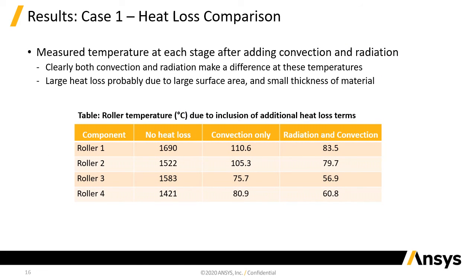So if we have a look at this table of temperatures, we'll see why the different types of heat loss are important. If we look here in the first column, we see that if we just look at the heating due to the eddy currents, we end up with very large temperatures. These are extremely large, and the material is virtually going to melt at this point, so it's just not practical. But if we now include heat loss through convection, we get a significant drop in the temperature. And then if we include radiation, we get an even further drop in the temperature there. Okay, so in this case, both convection and radiation are very significant mechanisms for losing heat from the system, and we do need to include both of them. The significant drop from convection is most likely due to the large surface area and small thickness of the material used, at least in the arm and the mast material.